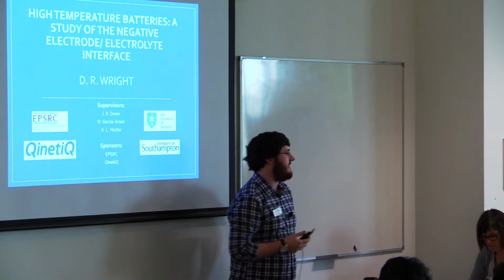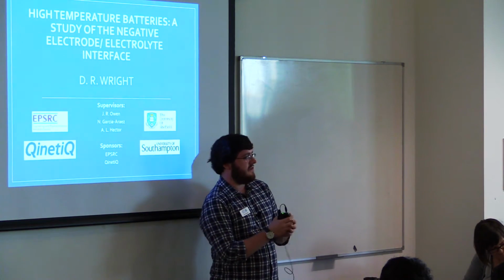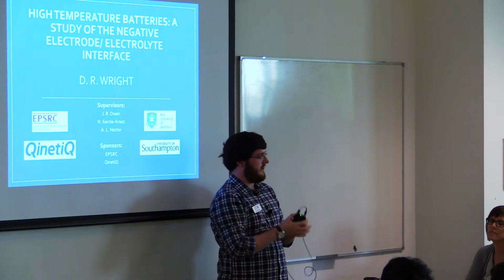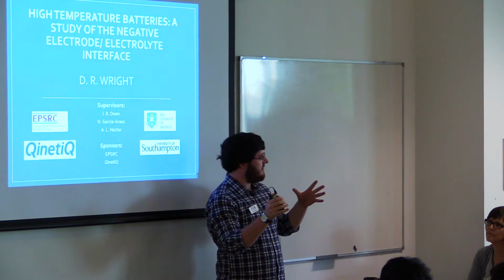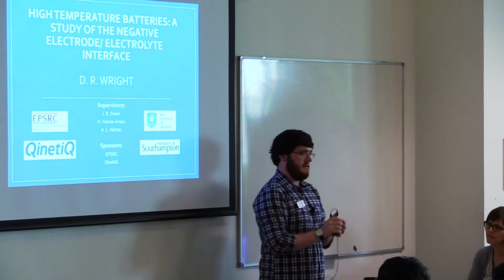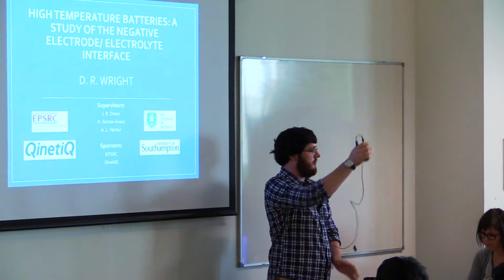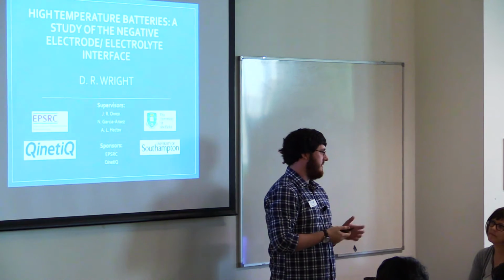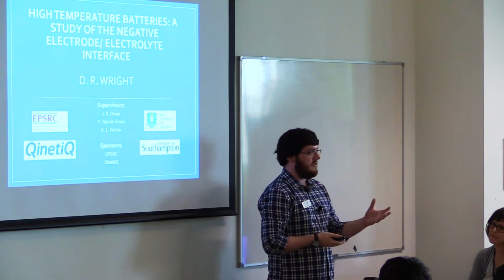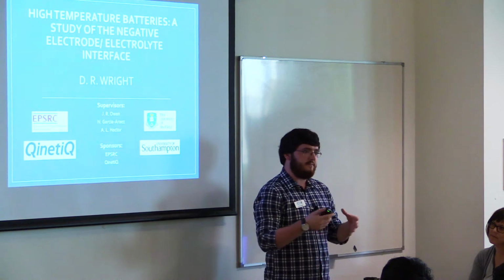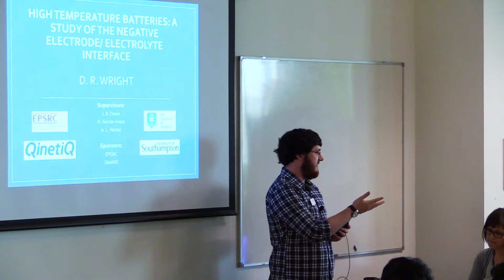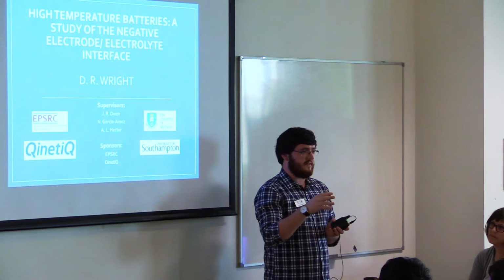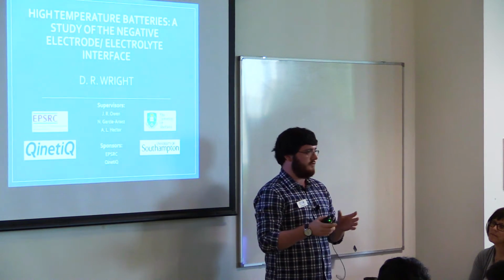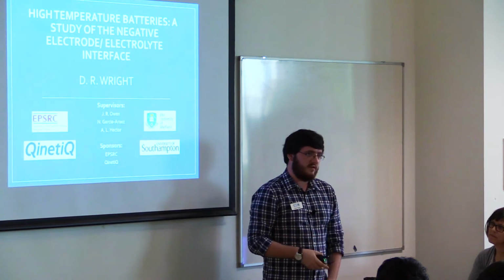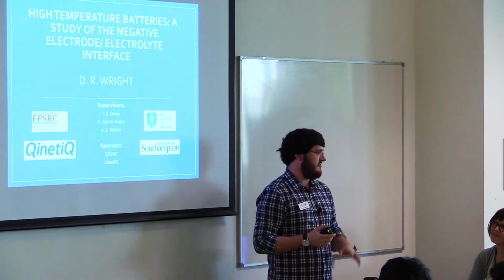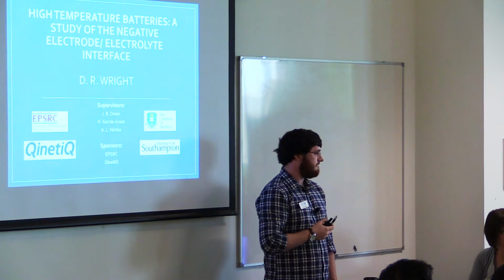Well, that comes down to different nanostructures. When they do silicon nanofibers, it's really narrow, so it only expands, I think laterally would be the word, and they can better accommodate the expansion rather than it expanding in every direction. They can control which way it expands and accommodate for that. Silicon nanotubes, again, and equally you can contain your silicon within an inactive matrix. I think they can use silica structures, and they coat the silicon onto the surface of that. The silica doesn't expand, the silicon does, but it's contained within this inactive matrix, so you don't get the cracking that I demonstrated.